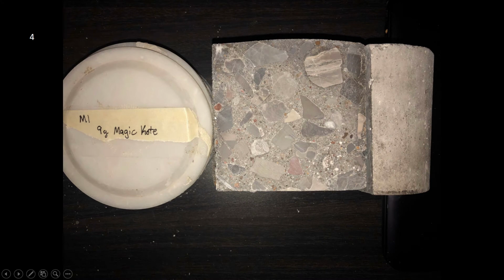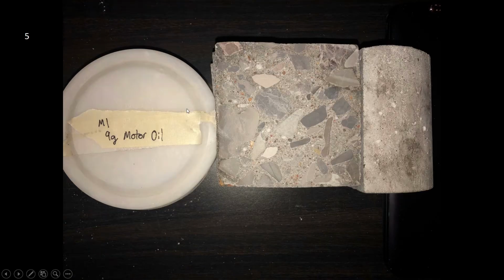You can still see it's eating away even more at the surface area, and it's starting to penetrate into the concrete a little bit. Our fifth sample is 9 grams of motor oil applied to the cylinder. As you can see, it's really eating away at the surface area of the concrete. But our cross section shows relatively no difference.